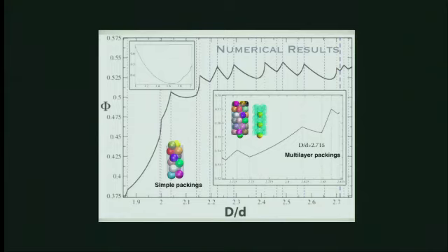What we're doing is essentially making the cylinder diameter bigger and bigger and asking what the densest packing inside there is. In the limit that you go towards infinity, the influence of the boundary becomes negligible, and therefore you expect to recover an FCC lattice. That would be my intuition. How many contacts does each sphere make in that limit? In the FCC limit, 12 contacts.